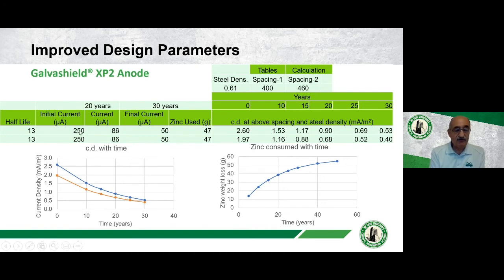If that was 15 degrees higher, this is another thing that we worked out, and I forgot to mention, is that for every 15 degree Celsius increase in temperature, you get a doubling of the current, or halving if you're going the other way. So if our temperature is a mean of 20 degrees instead of 10, that will be 500 microamps.